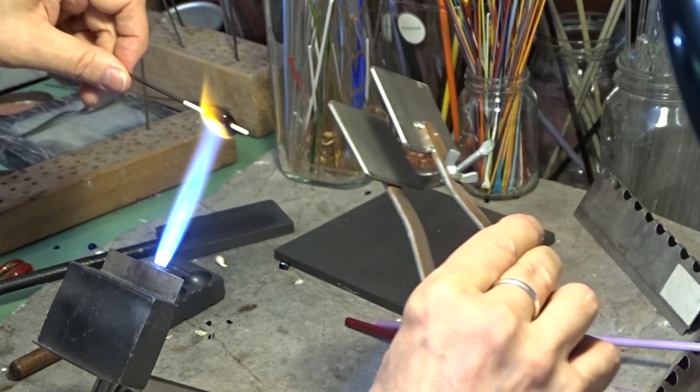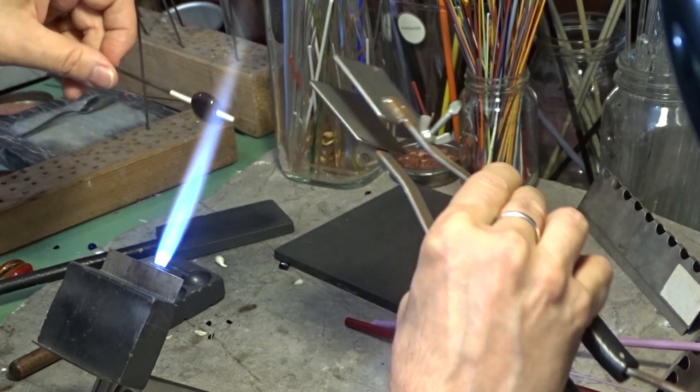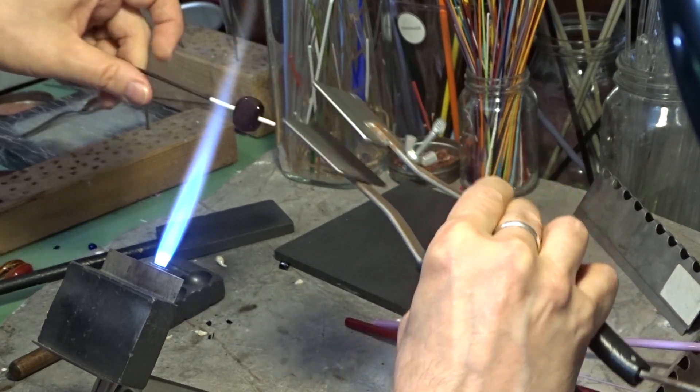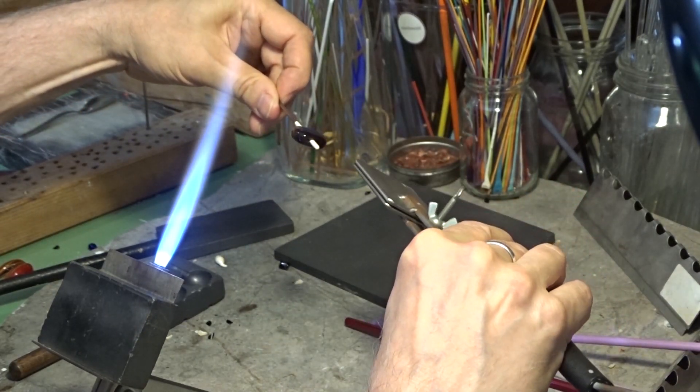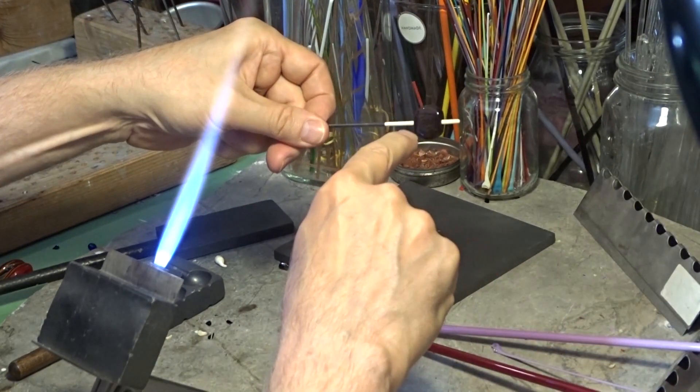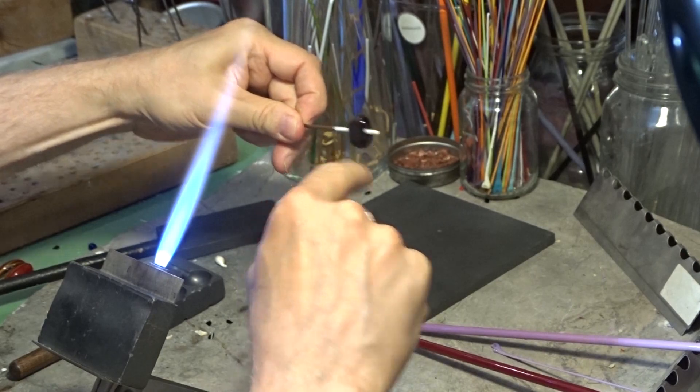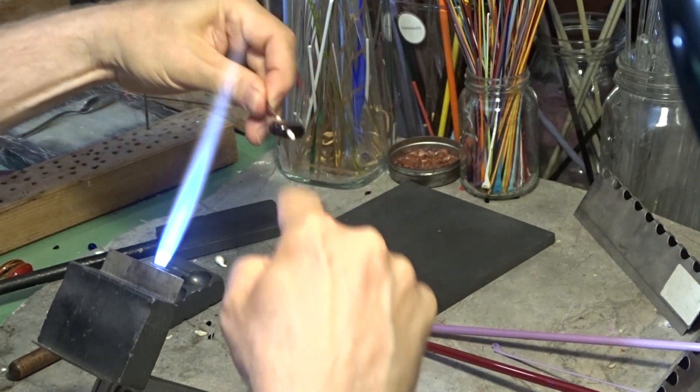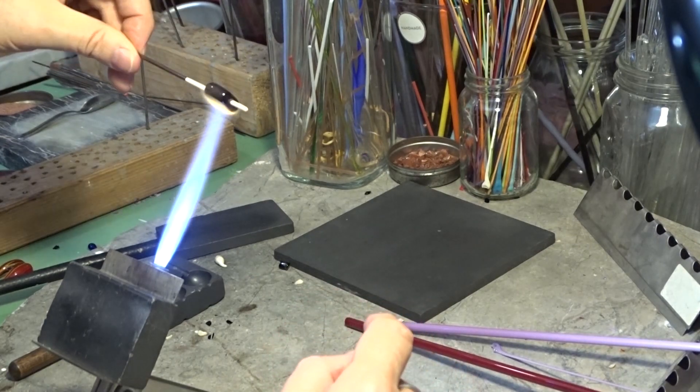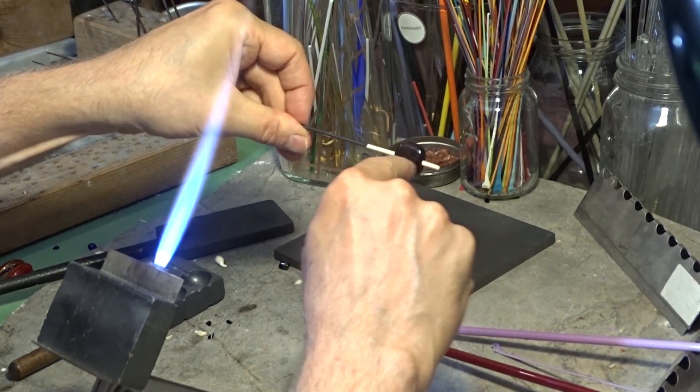This one, I always have two, because sometimes instead of a fixed height, I want to be able to squish it as much as I want. However, I never want to squish it so much that I create a super thin amount of glass at the top, above and below the bead hole, because that can really make for a break point.